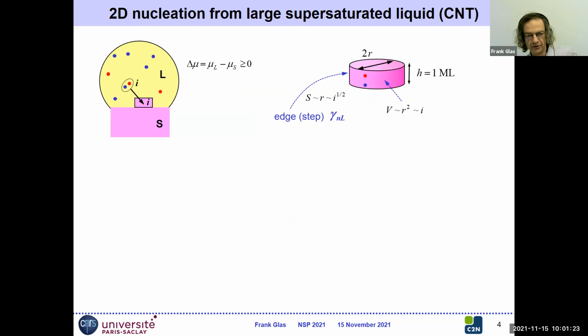So I start with very simple ideas. A few facts about nucleation, 2D nucleation from a large supersaturated liquid. So this will be our reference. Here we don't take into account the small size of the system, but our liquid is supersaturated, which means that there is a positive difference of chemical potential for a 3-5 pair between the liquid and the solid, the supersaturation. And we can calculate the work of formation of an island, which contains I pairs. So I transfer I 3-5 pairs from the liquid to the solid.